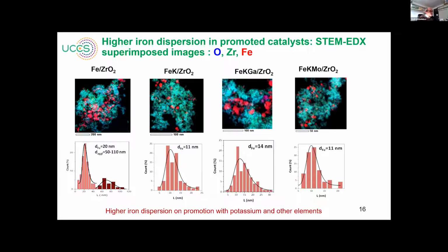Then we followed iron dispersion, meaning iron nanoparticle size, using scanning transmission electron microscopy with EDX analysis. And what we found, if we compare our catalyst to the reference, for which we did analysis of several catalysts, is that the addition of promoters, especially potassium, results in a significant increase in iron dispersion. If we look at the histogram of particle size, we have a decrease in particle size from 20 to 14, 11 nanometers.